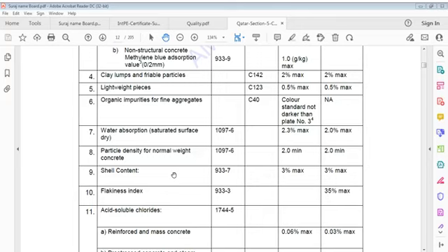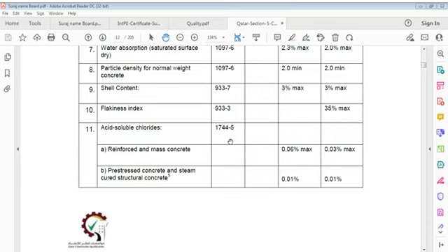Water absorption, saturated surface dry, that is BS 1097-6. Water absorption is 2.3% maximum in fine and 2% maximum in coarse. Particle density for normal weight concrete, 1097-6, 2 minimum. Shell content, 933-7, is 3% maximum. Flakiness index, 933-3, is 35% maximum.